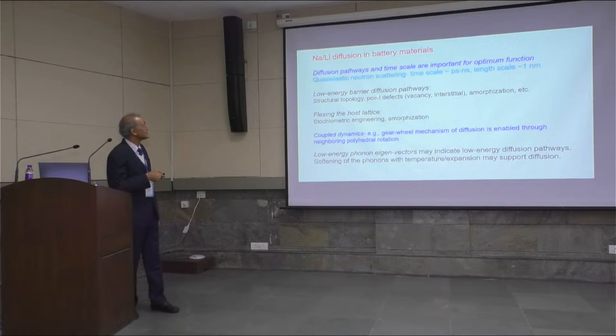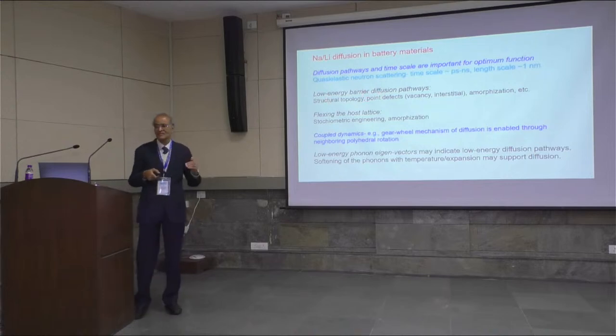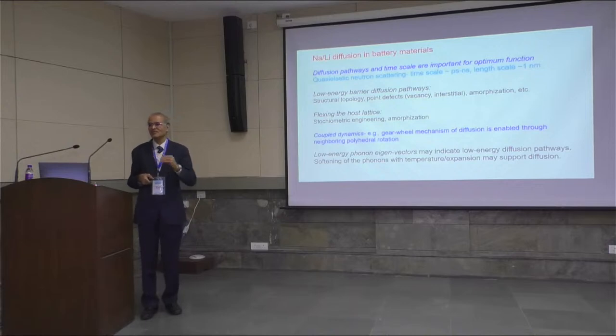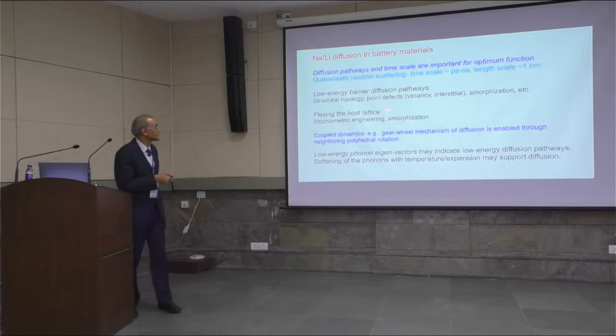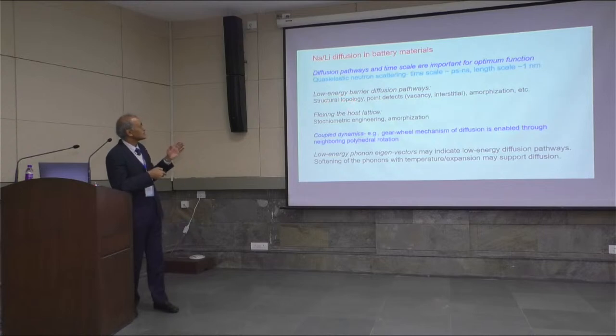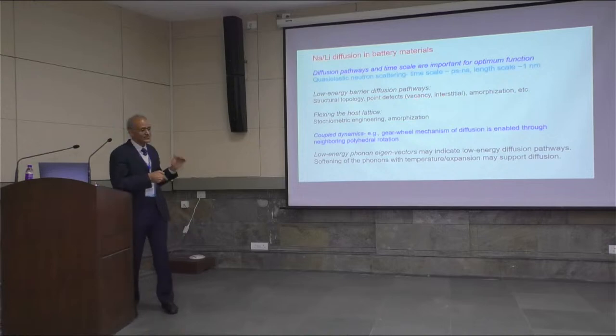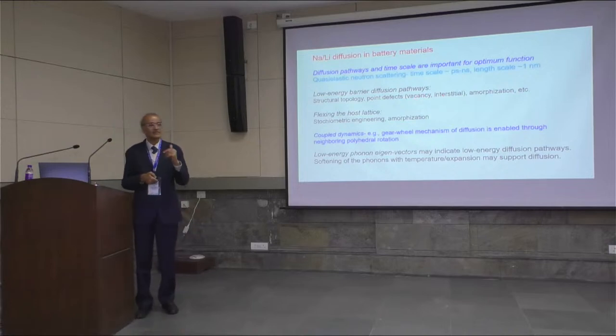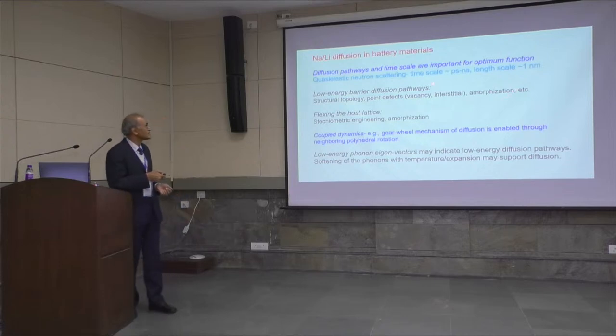And then you can very well imagine that you are looking for low energy barrier diffusion pathways. If the energy barrier for diffusion is small, then those will provide the preferred pathways. And that is what we would like to find out within the materials. These can be helped in various ways. The structural topology, I'll take an example. And the point defects are useful because the vacancies or interstitials help in the diffusion process. Another important thing is if you have an amorphous kind of structure, that has its own benefits.